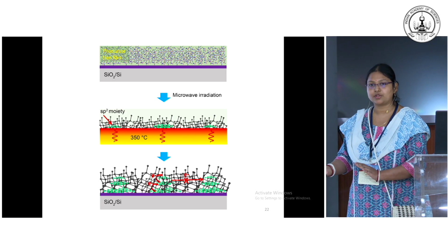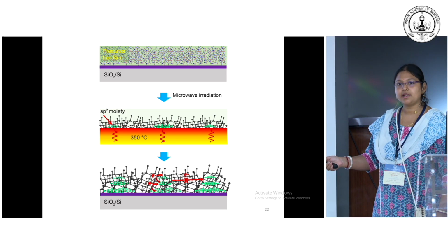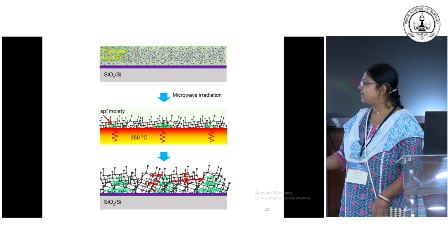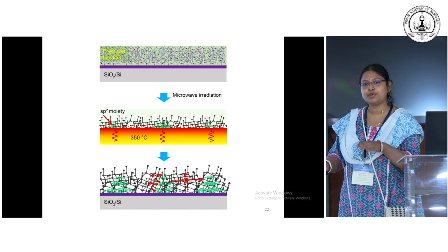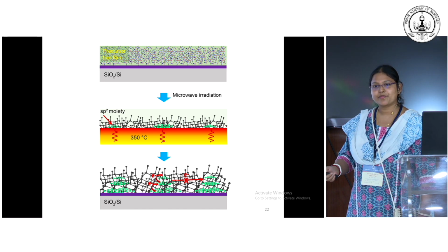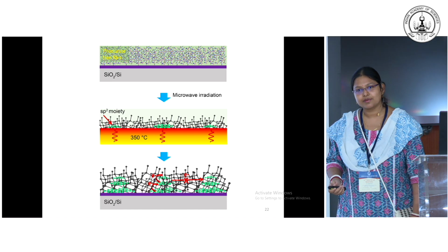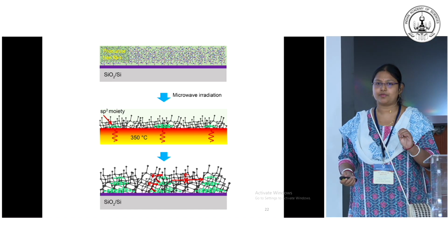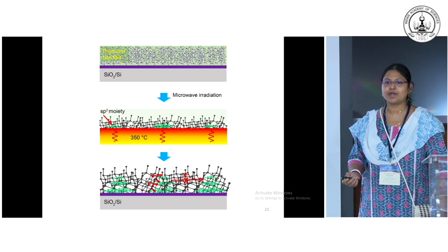Yes, sir, it is very much thickness dependent also. We have shown that when it is very ultra thin, less than 20 nanometer, then it is vertically conducting, but gradually it becomes like insulating. So it's an amorphous structure with partial crystallinity. Yes, there are very small grains of graphite. That's why conductivity is different.